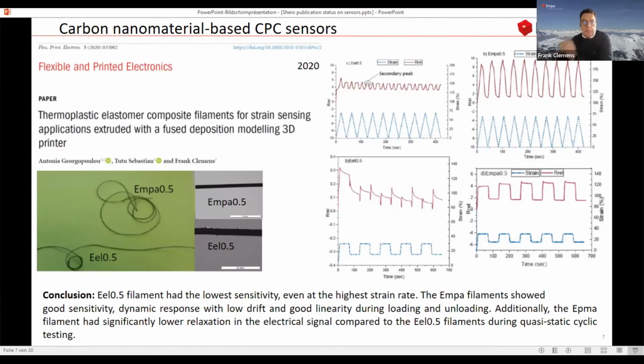However, you could say, okay, look, I use different technologies to know exactly what the slope is, and by this I read out my sensor. But if you do this quasi-static cycle experiment, which sometimes happens, so you move, for example, your robot, and then you stay at a certain position, you see that you can almost not neglect or select anymore in which state you are, because it's just these peaks which you can see very nicely when you change the strain inside your material. And this is, for example, due to the change of the charge density in the material.